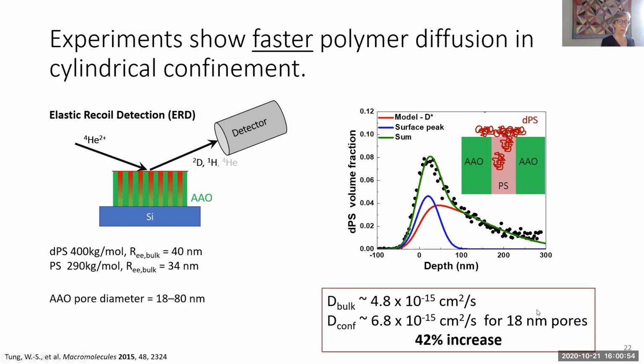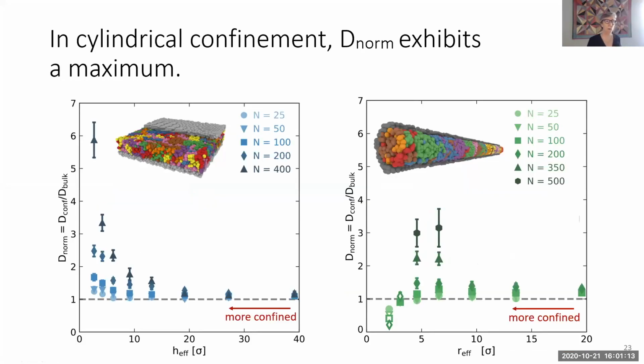Right? So it's 42% in this particular case. So it's an 18 nanometer pore. It's a pretty small pore. And it's going 42% faster than it would if it was going into a homogeneous bulk polystyrene. And so that's consistent with what we saw for the thin film. So let me show you now what we saw for the cylinders. And it's kind of the same.